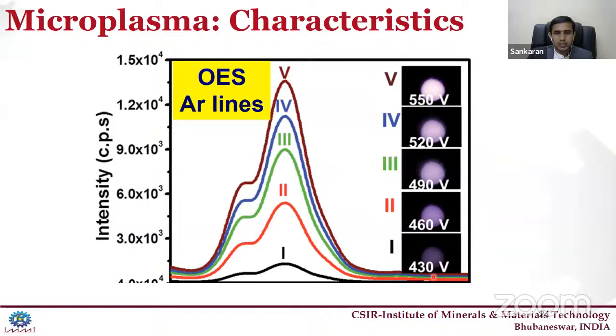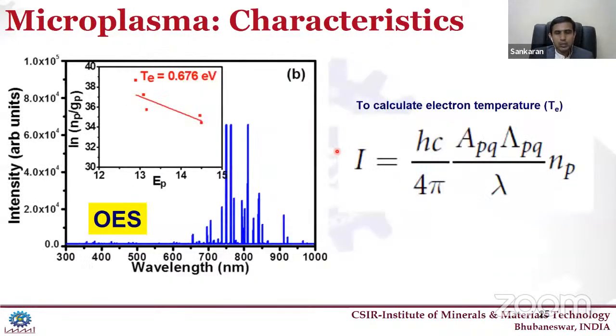Also, we can see the intensity of the plasma increases. The spectrum that we obtain from the argon lines also increases. So intensity values also increase. So these are the next studies with which we can characterize the microplasma. And the third one, from the OES, this is the optical emission spectroscopy of the argon lines.